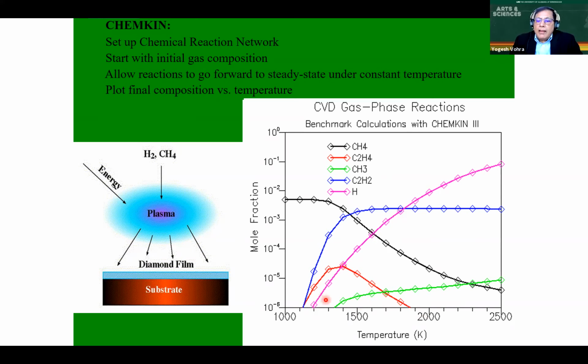One thing to pay attention to is this purple curve, which shows us that the atomic hydrogen increases a lot, by several orders of magnitude, as we increase the gas phase temperature. Another thing to note is the CH3 radical with this green curve, which picks up as you increase the gas phase temperature. And then, of course, you have a short-term burst of ethylene, and then you also have acetylene, C2H2, in the plasma. So you can see that plasma is producing some of these activated chemical species, which can give rise to novel material deposition.